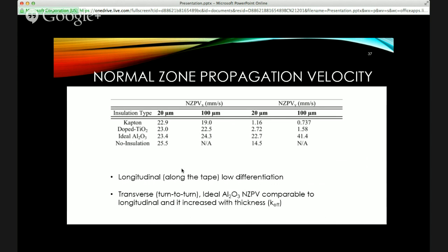Okay. So on to the normal zone propagation velocity, the X direction in this case, if you can see the subscript X, it is along the tape, so that's the longitudinal direction. And there, because the quench tends to develop along that direction anyway, you don't really see that big of a difference in the values.